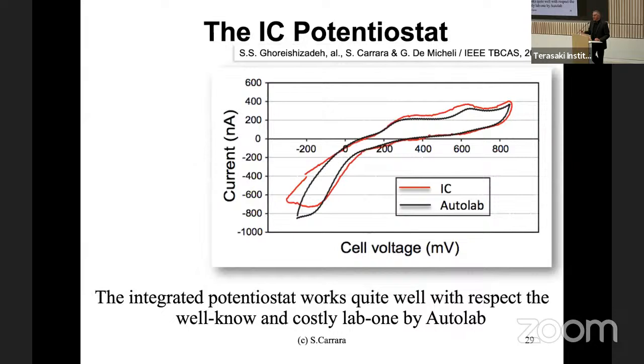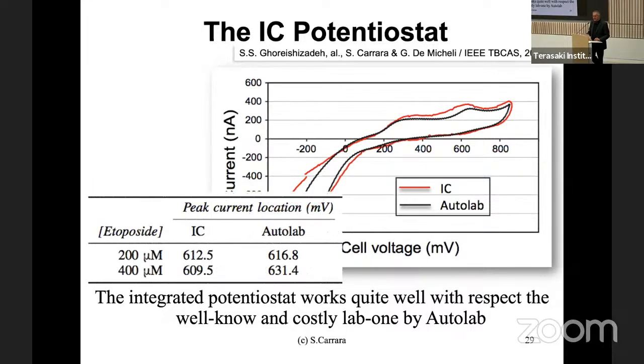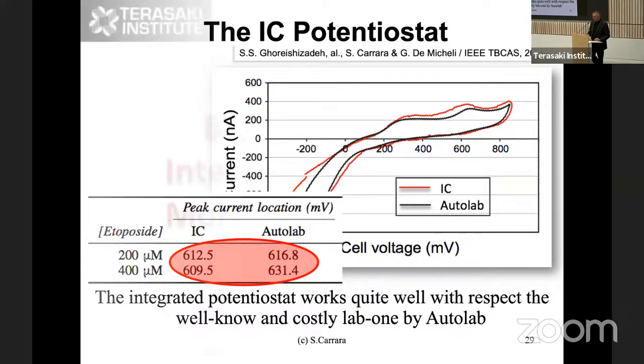In the case of drug detection, I'm sorry I have no time to show you details, but we really need to measure the Faradaic peak. It's usually not sufficient to do chronoamperometry. So the comparison was done with etoposide, a very well-known anti-cancer compound. You see two peaks very well detected, both with the Autolab and with our electronics. So it seems we are in business. Again, the issue here was to find correctly the position of the peak while changing the concentration, for example. You see the comparison is fairly good between reference lab instrumentation and our electronics.